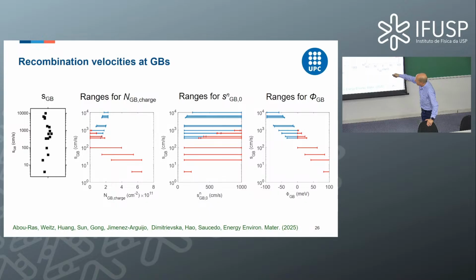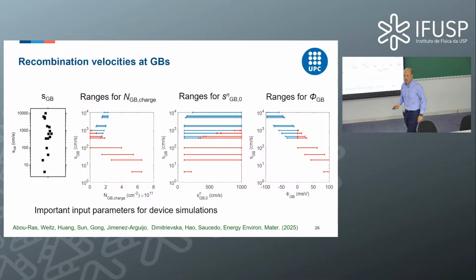And in some cases, you cannot tell whether it's downward or upward band bending. In some cases, it can be both. But you can find corresponding ranges for the prefactor and for the excess charge density, which means that you have a corresponding range for the barrier height. This is better than nothing and is an important input for device simulations. I will show you at the end of the talk.